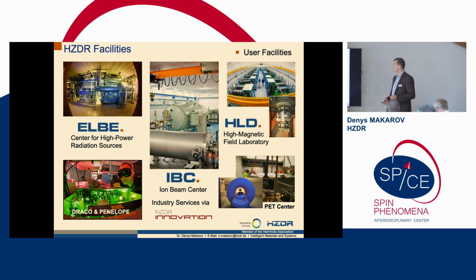You can modify properties of your samples. Today we heard from Kai about a very exciting possibility to manipulate properties of the sample simply by putting hydrogen in your material, like palladium adsorbs hydrogen. In this case, you can do a permanent change with, for example, implanting heavy or light ions, magnetic or non-magnetic ions, in your magnetic samples in order to modify their properties. Spin-orbit coupling or exchange interaction can be modified by ion beam implantation.